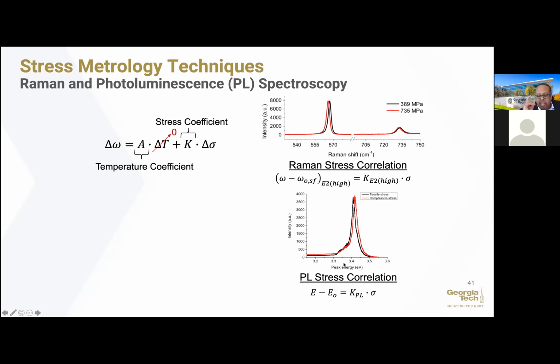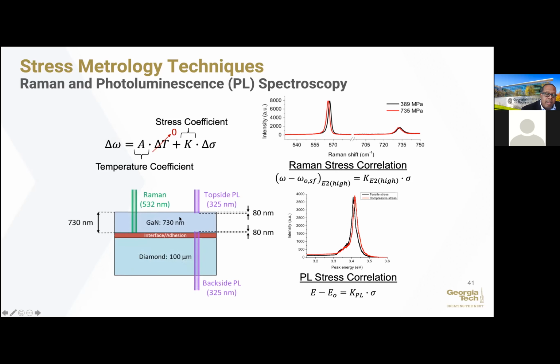The other one that I'm going to show you is photoluminescence. Again, the band gap of the material will also shift with strain or with stress. And so I can also use photoluminescence to measure right at the top in order to get a stress measurement at the top of the device. So here I have my gallium nitride on diamond. What's nice is that the diamond is transparent to my UV laser. So I can measure the surface stress right here at the back side with PL. I can measure the surface stress right at the top side using PL. I can measure the average stress through the thickness.